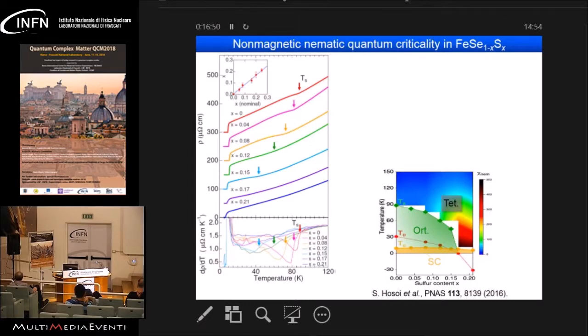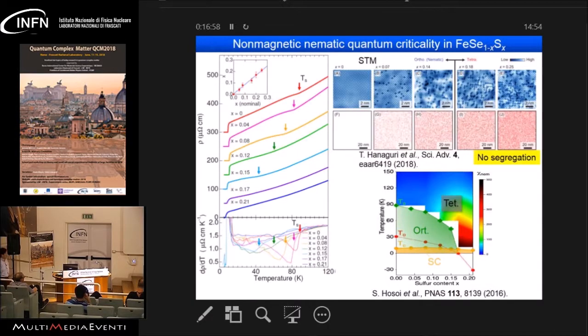And above 0.17, we got a purely tetragonal phase like this, okay? And actually, Hanaguri-san, my colleague, can look at the STM topographic data like this, and he can assign the position of sulfur by looking at this STM. And he can look at the wider view, and he put the points on the positions of sulfur, and as you can see, there is no evidence for any segregations, meaning that we have quite homogeneous single crystals.